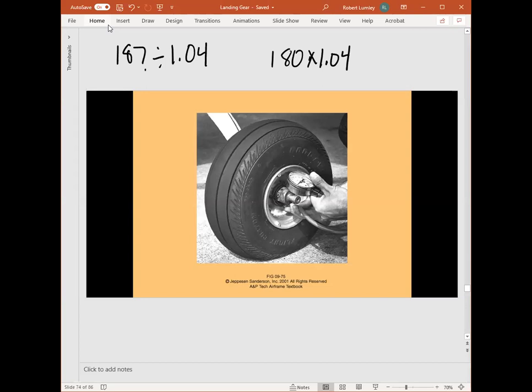So they specifically talk about nylon tires, that once you inflate the tire, you want to wait approximately 24 hours and then test the tire pressure once again and adjust it, because the pressure will drop about 5 to 10% over that 24 hours just due to the tire being stretched out. And so then we want to adjust and then recheck every 12 to 24 hours until the pressure stabilizes within that tire.